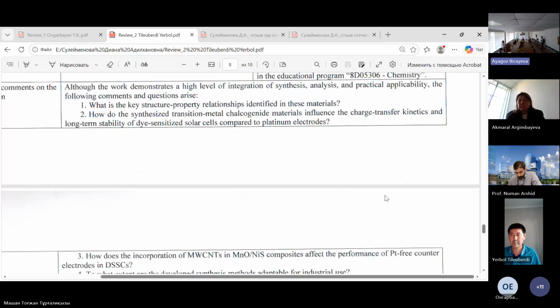Regarding question number 2, according to EIS and Tafel analysis, the synthesized transition metal chalcogenide-based counter electrodes exhibit faster charge transfer kinetics than platinum due to their higher electrocatalytic activity, large active surface area, and lower charge transfer resistance. Compared with platinum, these transition metal chalcogenide materials also demonstrated better long-term stability because of their high resistance to corrosion.